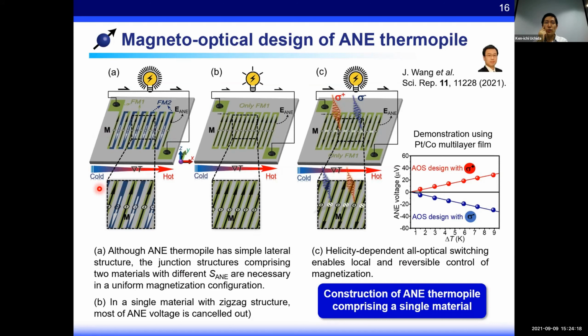So to overcome this situation, we used helicity-dependent all-optical switching of magnetization, which enables local and reversible control of magnetization by irradiating a sample with circularly polarized light. So by alternately reversing the magnetization direction, we can avoid the cancellation of anomalous Nernst voltage in the single material. A single material works as a thermopile. We have clearly demonstrated this concept experimentally. However, the obtained thermopower is still low. So the principle elucidation and material development for higher thermoelectric output is necessary.